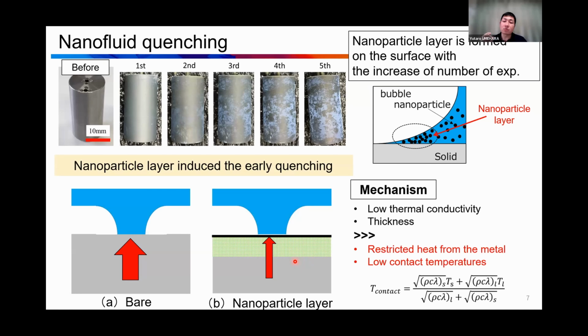So the mechanism is the low thermal conductivity of the nanoparticle layer, and also its increased thickness is the main reason. Finally, this thickness and the low thermal conductivity of the nanoparticle layer restrict the heat from the metal inside, and then finally we can get a low contact temperature. This is the main mechanism of the reduction of the cooling time when we use the nanofluid. The contact temperature is like this. Here is the thermal conductivity. When we get a small value, finally we get a low contact temperature, and this low contact temperature induces early quenching.